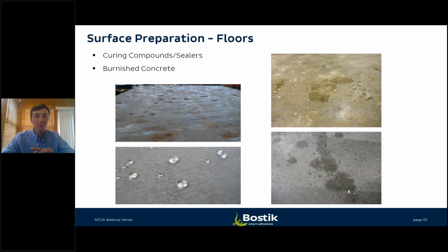In the case of a lot of concrete construction, you see curing compounds and sealers. You'll find burnished concrete, although there's a variety of ways to continue dealing with those in the marketplace as it pertains to gauge porcelain. But you can see in these couple of images, the top left, an adhesive that has been bonded to a curing compound, and you can see the little reflective areas on the back of this adhesive. So this is the back of a flooring material that debonded, and you can see the curing compound on the face of the adhesive, which is the evidence of that bond breaker or bond inhibitor that caused a failure or contributed to a failure.